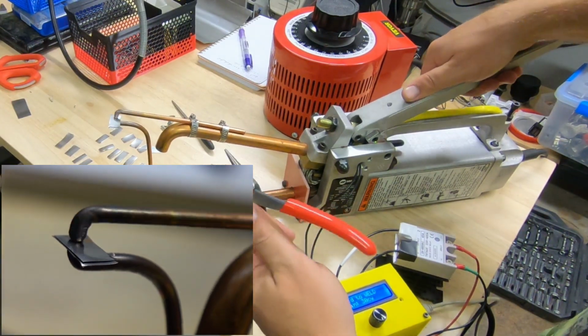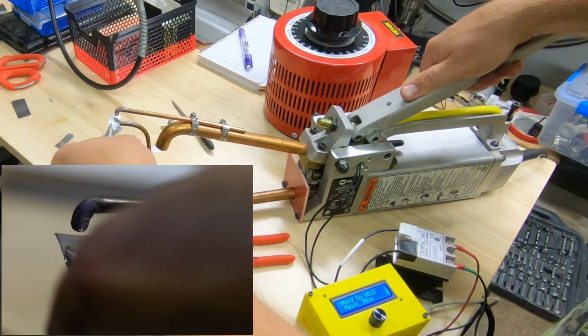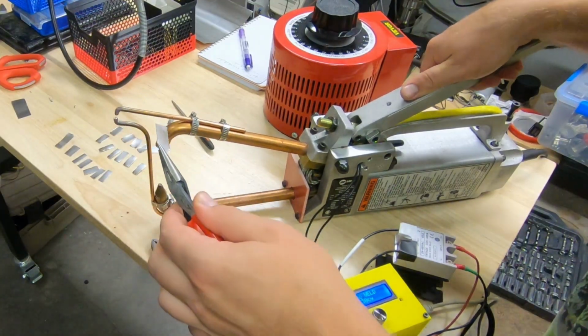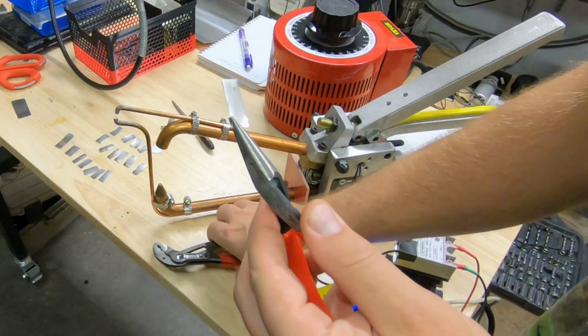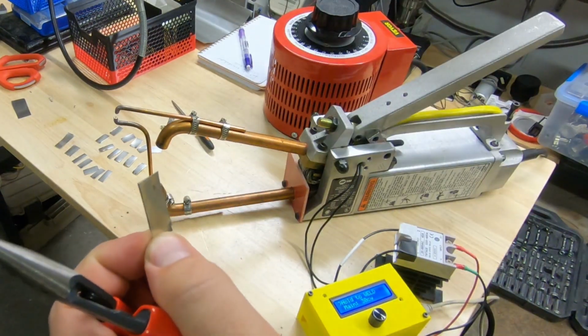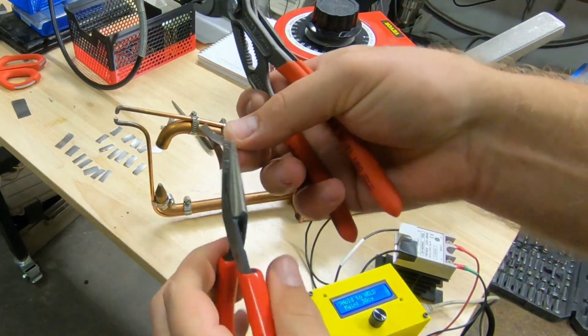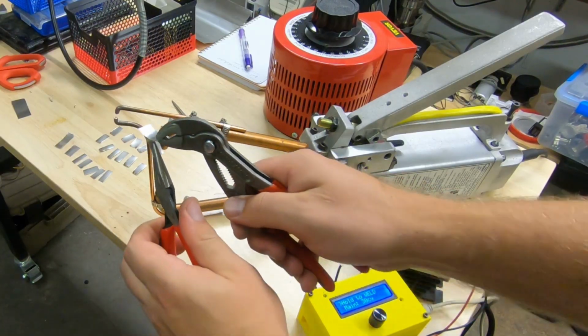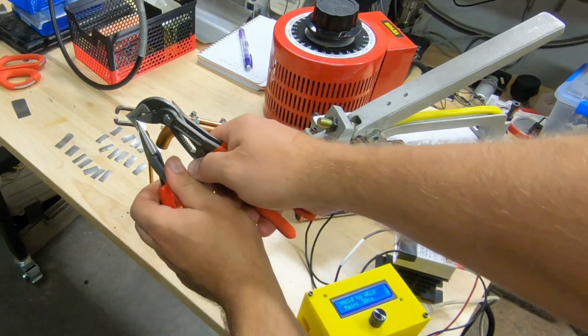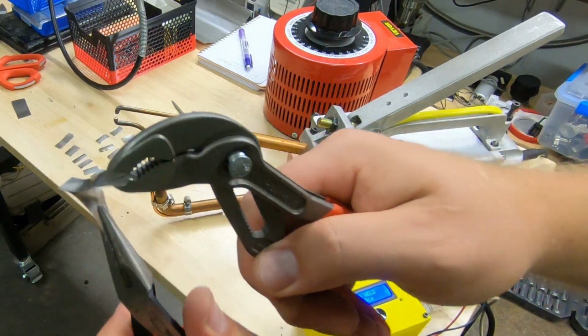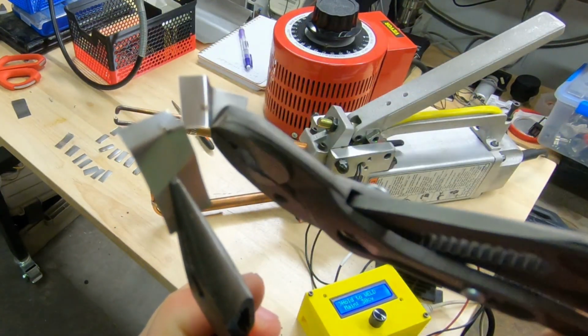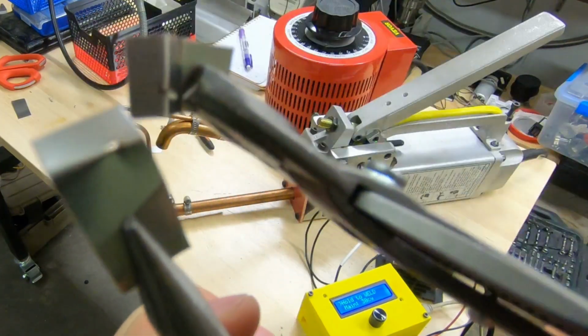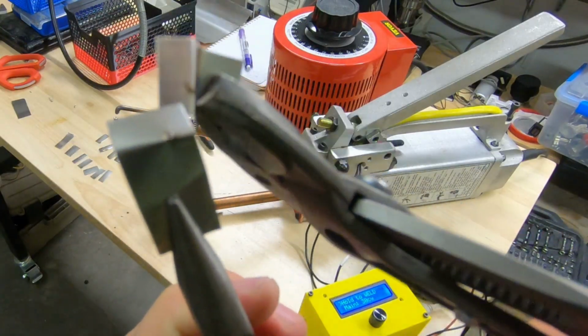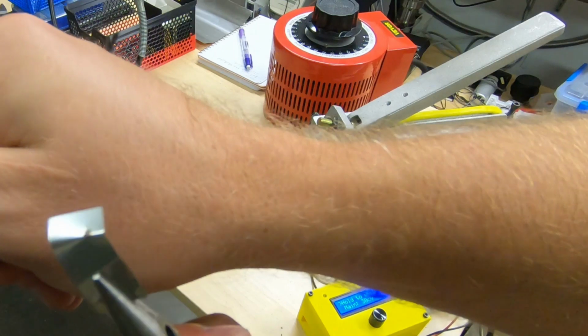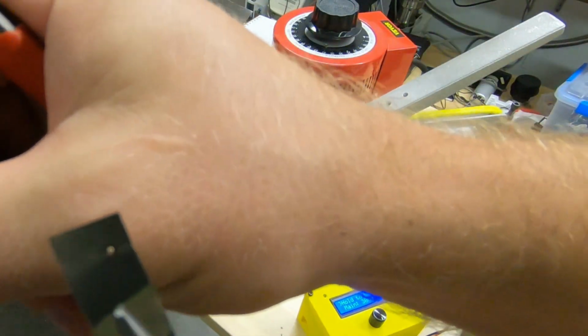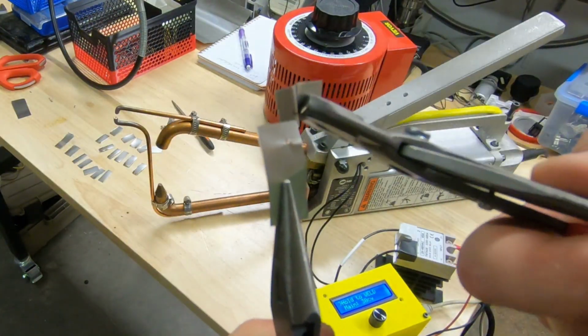Okay, I bet that's too long. Oh, maybe not. Let's see here. Yeah, it's still getting a little bit stuck to that bottom electrode. So the weld itself is pretty good. Yeah, it's kind of hard to see, but basically there's a little hole in the foil now where the weld was, so it failed around the foil rather than at the weld.